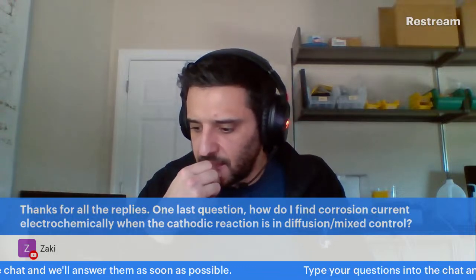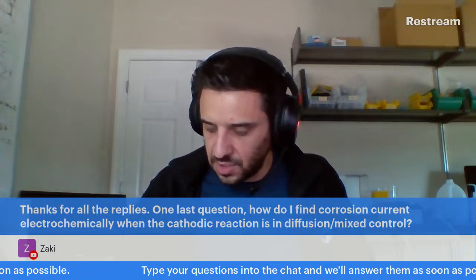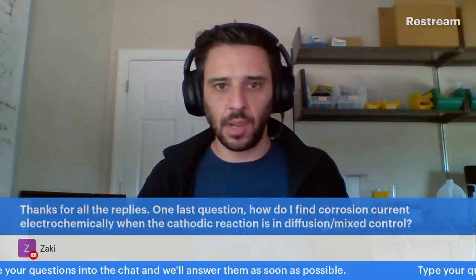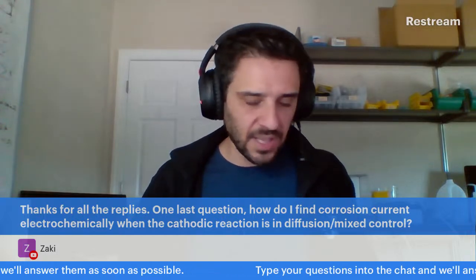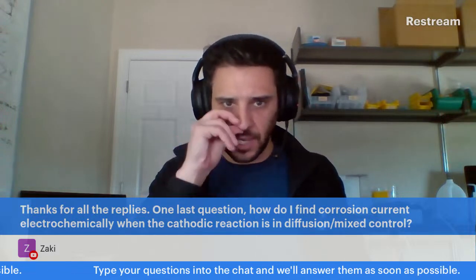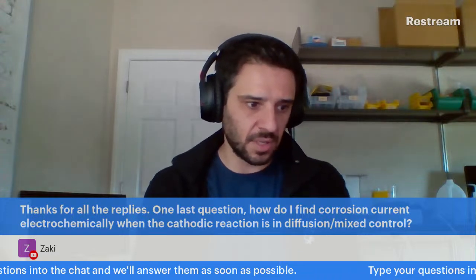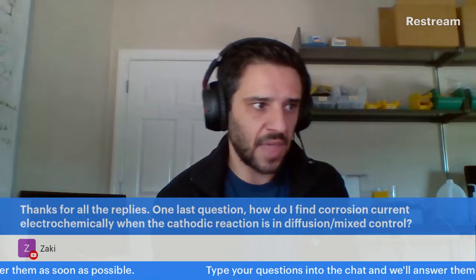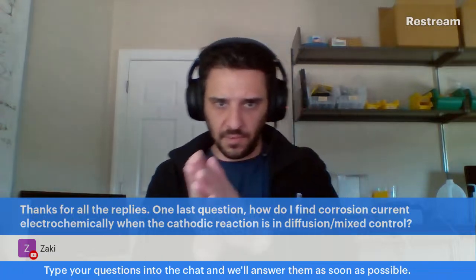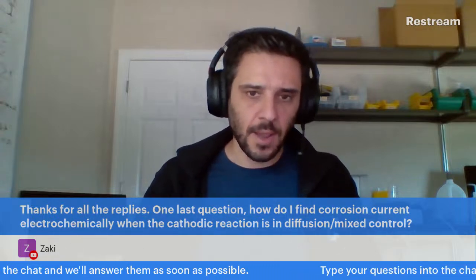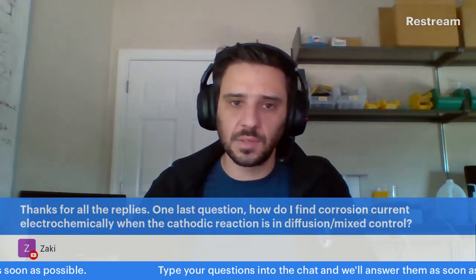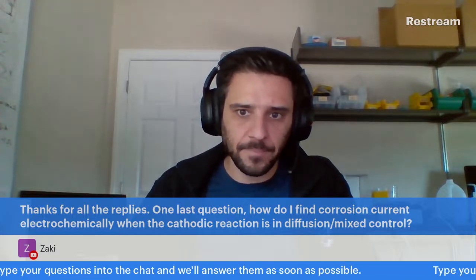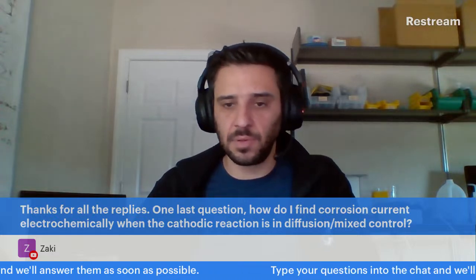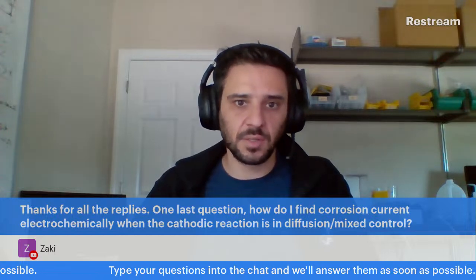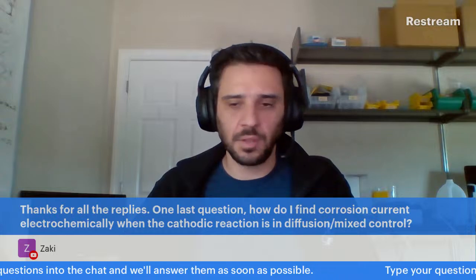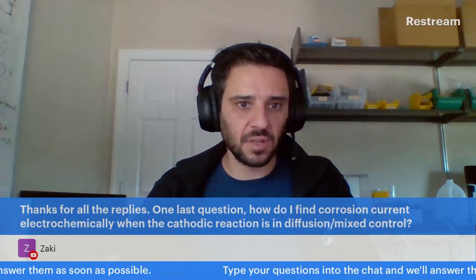If you do have a lot of diffusional effects interfering in your voltammogram, for instance, the only way is to deconvolute the data in a Levich kind of way, where you use some fundamental equations that allow you to isolate diffusion limited current from kinetic current based on the rotation rate and other constants associated with your system. Beyond that, honestly, people very often use the current directly from their voltammogram to get kinetic information, either through a Tafel plot or for corrosion. In the corrosion field, it's actually quite common to do this.